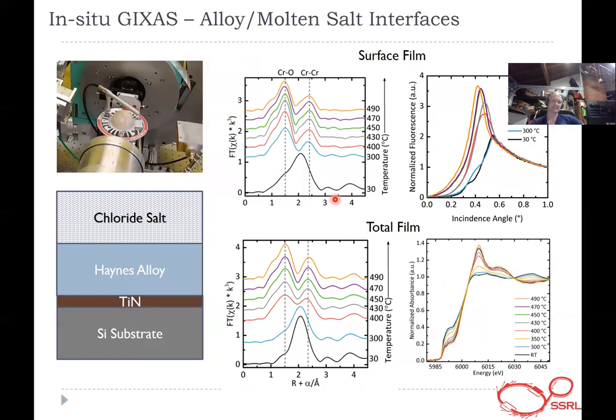Also, we've used the same kind of technique to look at alloy molten salt interfaces. Molten salts, or chloride molten salts, are gaining popularity for use in solar energy. We were tasked with characterizing how a Haynes alloy, which is a nickel superalloy, interacts with a chloride-based salt at elevated temperature. We were able to look at the chromium K-edge through a chloride salt overlayer at elevated temperature. And you can see the XAS of the surface and how that changes with temperature.